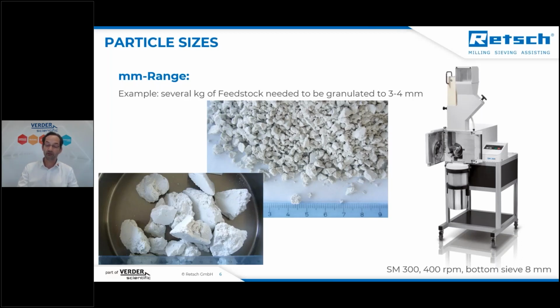And at a very low revolution speed of 400 RPM, we reduce the impacting of the material against the grinding chamber. And so the grinding takes place mostly by cutting and not by impacting. So the particle sizes are precisely defined. So as you can see here in this photo, there are very low amounts of fines, but the gross material is in this range of 3 to 4 millimeters.